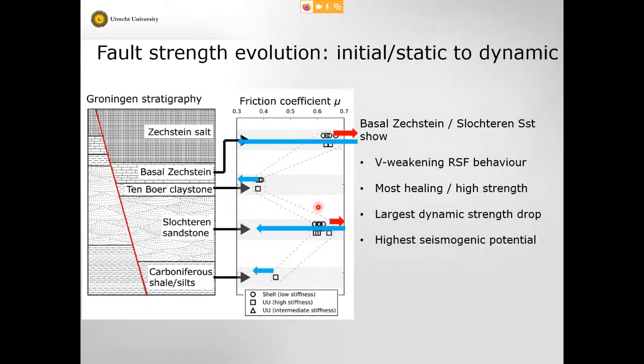But basically, the picture that emerges is here's the reservoir, especially on a fault where this material, this Carboniferous, is dragged down here. This would have high potential for earthquakes. And this material itself, this carbonate anhydrite material at locations like this, or where it is actually juxtaposed against itself on a fault, has high potential for earthquakes. So it's a high friction coefficient for the basal Zechstein, high friction coefficient for the sandstone, and that can dramatically drop when you have dynamic weakening.